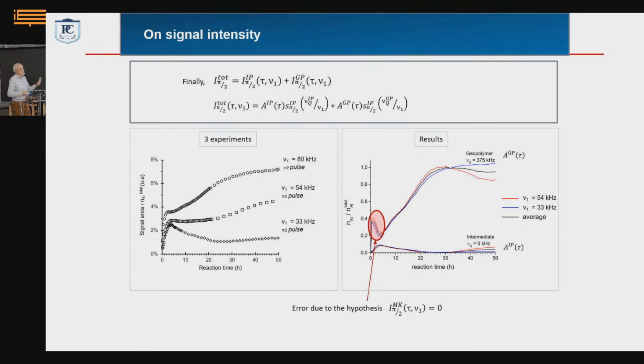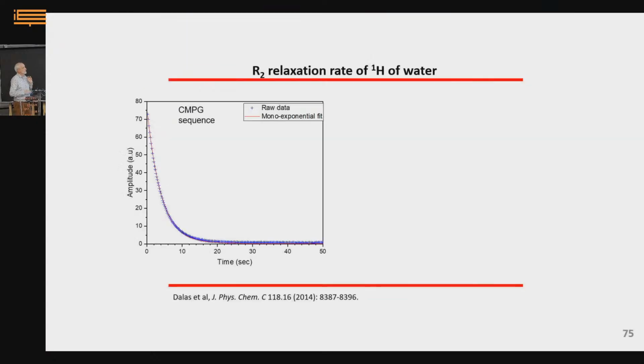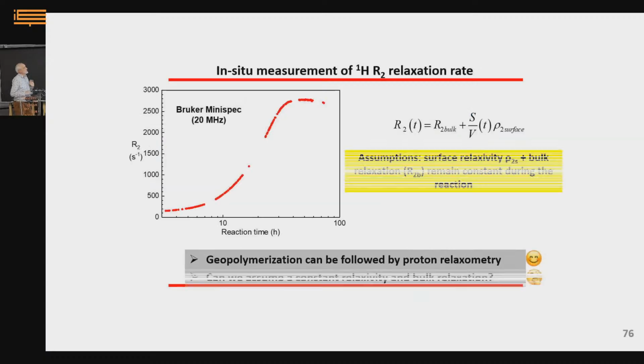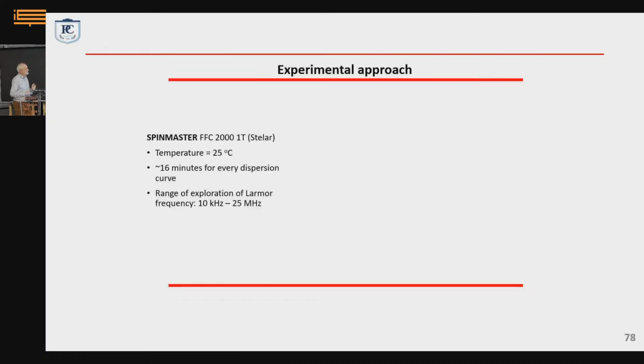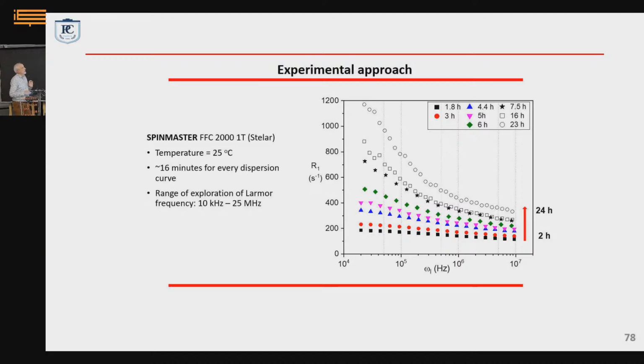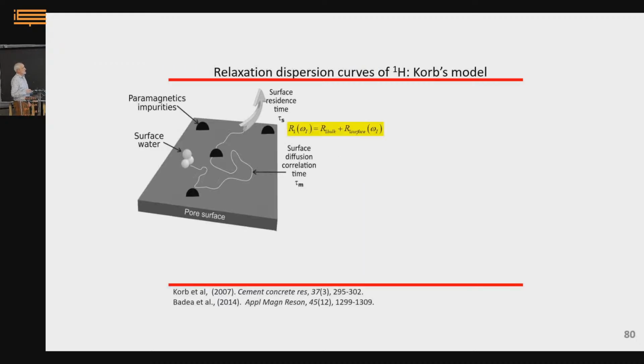It does, and for reasons that I don't have time to explain, the measurements are not accurate at very short time. So we have to resort to another measurement. Again, I go fast, which is relaxometry, where we follow the transverse relaxation time of the molecules of water adsorbed on the surface, of water in the paste, as a function of time and as a function of frequency. That is the NMR measurement frequency. Why do we do that?